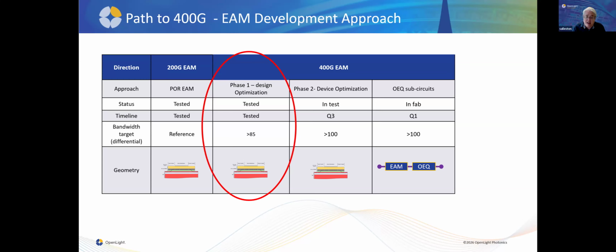Just as an aside, one of the other things that we actually have in test as well is an OEQ circuit. This is basically effectively a high pass filter with a low bandwidth modulator. This is another way of getting to higher bandwidths, but there is some control complexity and some additional circuitry. So what we're really shooting for is effectively a drop-in replacement of our existing EAMs, just with enhanced bandwidth to support those higher data rates.